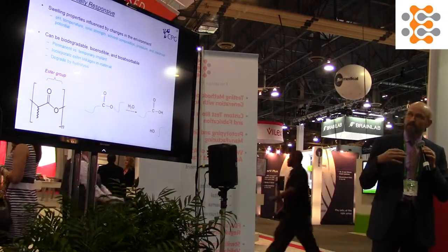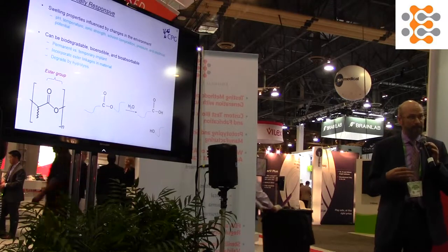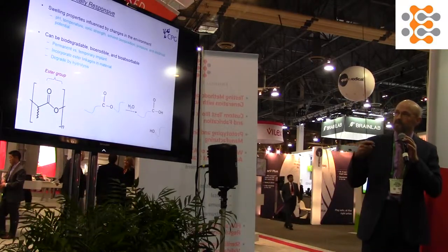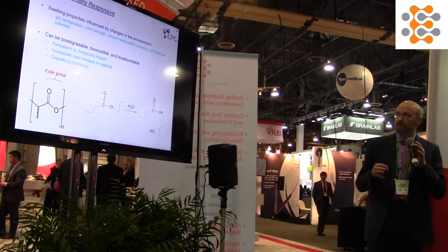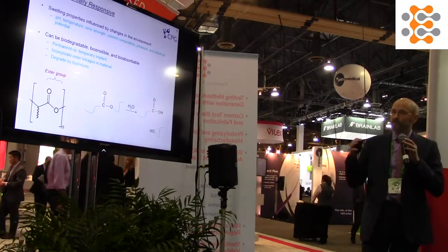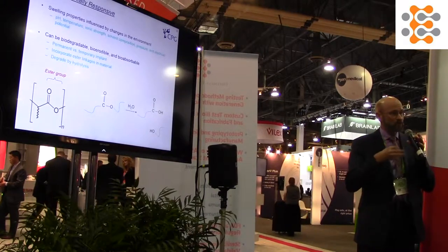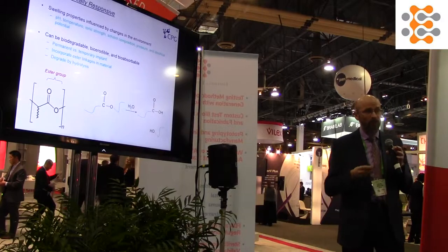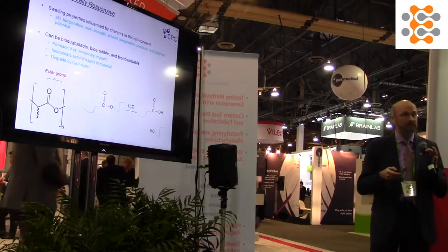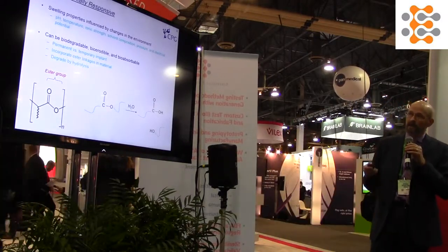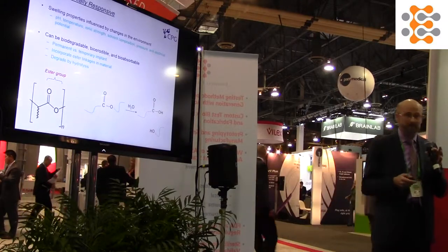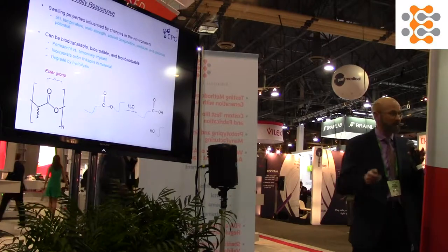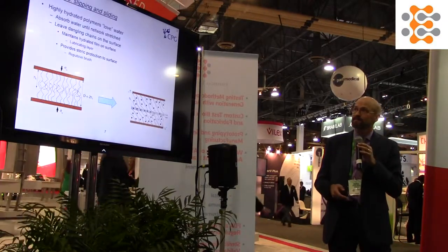We can make hydrogels so that they're responsive to the environment that they're put in, which is why they're great for biomedical application. They can respond to pH, temperature, ionic strength changes, pressure, electrical potential, and this is why when you put a hydrogel into solution or into the body, they'll either swell or de-swell according to the local environment, which is great for drug release or mechanical response. And we can make these materials biodegradable as necessary, usually by including ester groups which result in hydrolysis and break up the material in a controlled fashion.